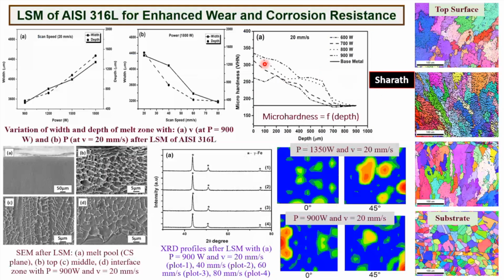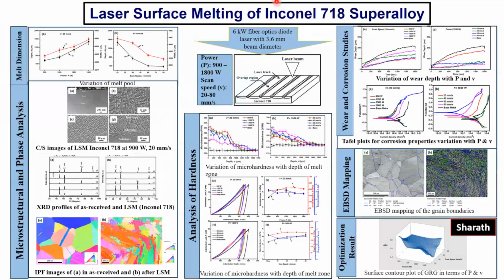Sharath recently got his degree, and he showed how surface melting vis-a-vis additive manufacturing can affect the properties of stainless steel, austenitic stainless steel, or Inconel 718 super alloy. So he basically first surface melted the alloy and then measured the properties. Then he did develop similar thickness structures by additive manufacturing, measured the properties, and compared.